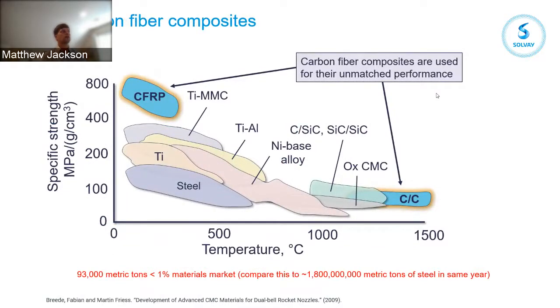When we look at carbon fiber composites, switching now from just the fiber to the composites themselves, you can start to see that CFRP, or carbon fiber reinforced polymers, tend to set themselves apart from other structural materials. When we look at strength normalized by density, so you take into consideration the weight of the structure and the strength, CFRP or composite materials are significantly superior to other types of structural materials. This obviously isn't a comprehensive list, but of the materials you'll see in aerospace, things like steel, aluminum, titanium, and even metal matrix composites, CFRP still stands apart when you look at structure per weight.